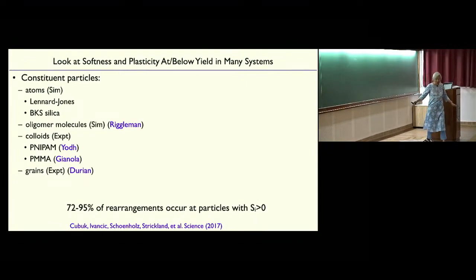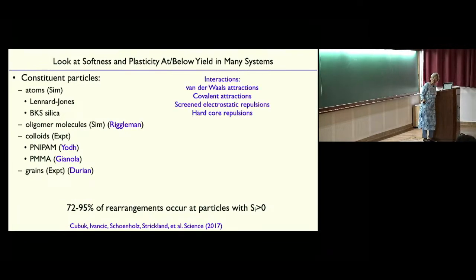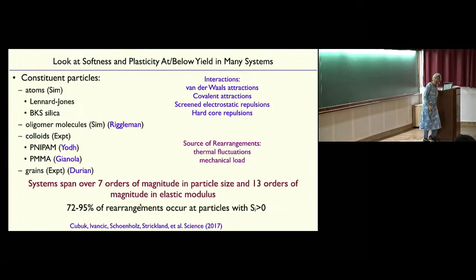If you look at many different systems, some are brittle, some are ductile, they have very different behaviors. We looked at simulations of atoms, Lennard-Jones, silica, simulations of short polymers. Experimentally, we looked at two different colloidal systems and grains and foams. In all of these systems, you can train for softness, and you find softness does pretty well for all of them. They have very different interactions, and the source of the rearrangements is very different. Some is from thermal fluctuations, some is mechanical load, but all of them were either below or near yield. And these systems, if you look at the particle size, it spans over 7 orders of magnitude.